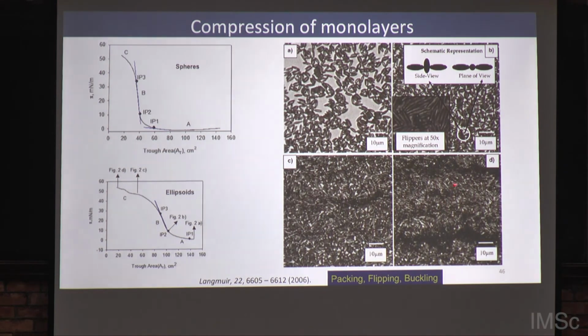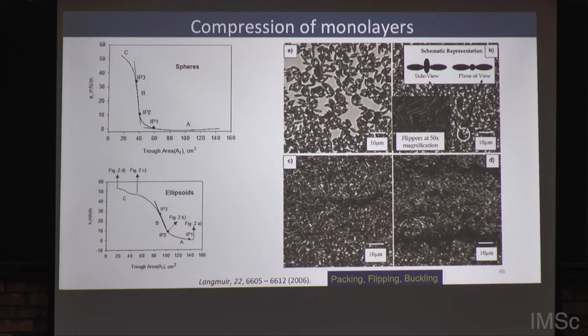And this is a case where the interface is buckled. This dark region that you see is because the interface is not planar anymore, there are some undulations, very similar to what you see for the case of spherical particles. However, we do see that when this wrinkling, this buckling happens, a lot of particles are lost to the interface.